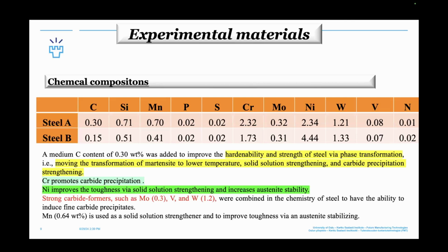Nickel is not a strong carbide former. We have molybdenum, vanadium and tungsten in both, but the main difference is in carbon content and nickel content, because this steel will enhance poly-martensite. This will have an almost dual-phase structure, martensite plus 50% bainite.